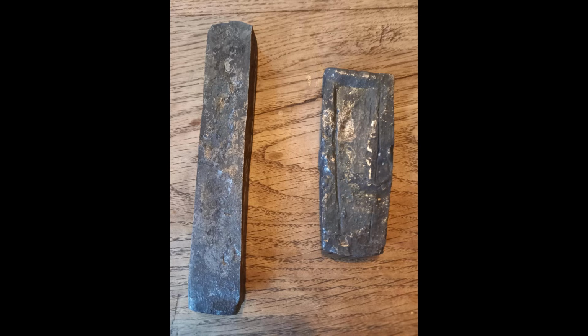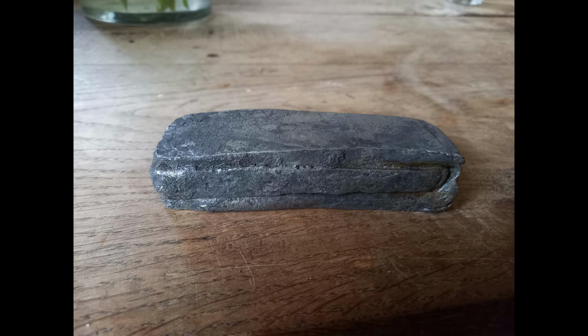Here we see the core bar of bloomery iron mixed 50% with half refined steel, which is further folded and welded 4 times, around which an edge steel of fully liquefied half refined steel is forge welded already. On the left we see the cover panel, which will subsequently be forge welded around the core bar and the edge steel. This is the way the Ulfberht swords were made historically. Here we see the entire billet ready to be forge welded into a single bar. Note how the edge steel is slightly protruding out of the middle of the billet, but is fully encased by the cover plates.